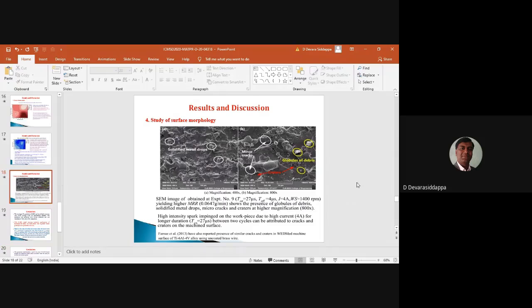This shows a SEM image of the titanium alloy obtained after machining at the cutting condition corresponding to experiment number 9, which yielded the highest MRR in the experiments conducted. As you can see, there are two figures at two magnifications. At the higher magnification, we can see that the surface is characterized by some craters and also some cracks. The presence of cracks and craters can be attributed to high intensity sparks impinging on the workpiece due to higher current.